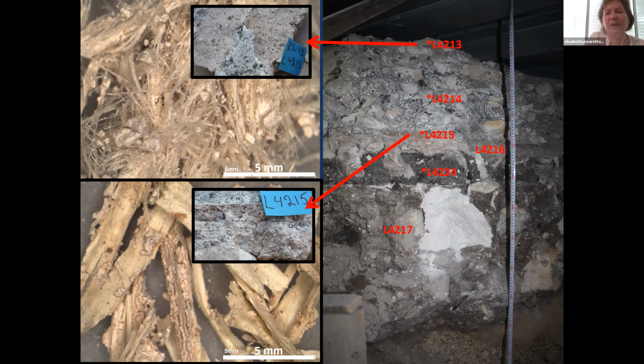These are 5 millimeter, and you see that this straw is very small, and we had to collect a lot because we still wanted to check that this straw is still a cellulose, as it should be initially, and indeed by checking that this is still a cellulose, then we felt confident that dating this straw would date the construction of this structure.